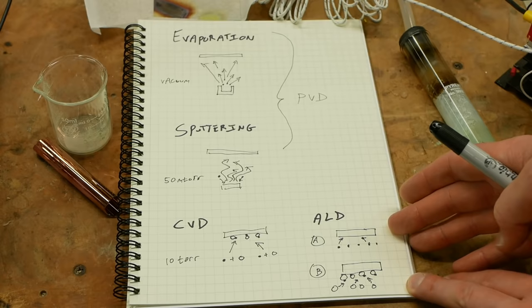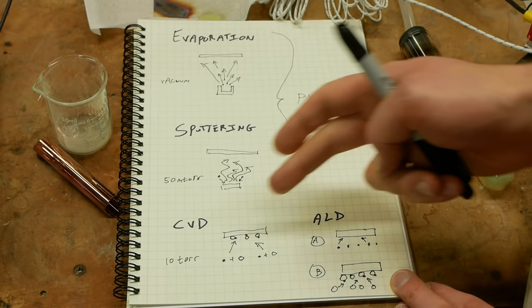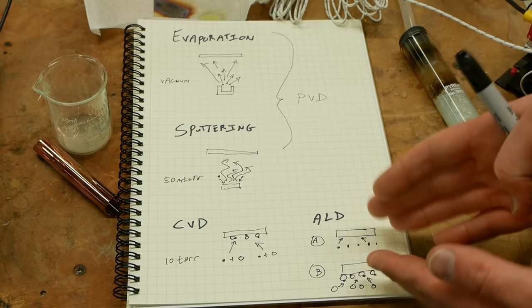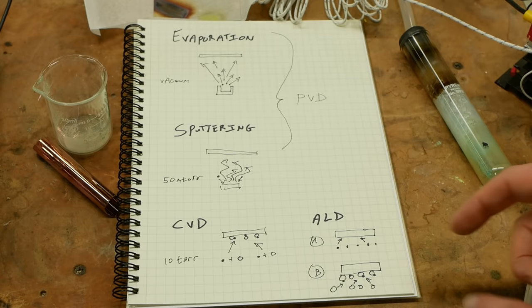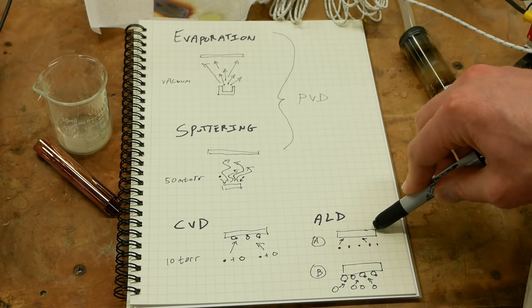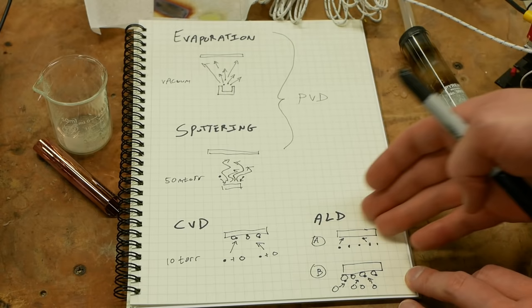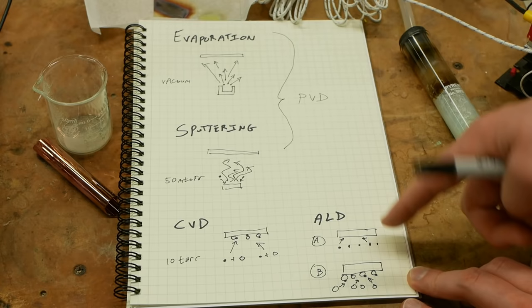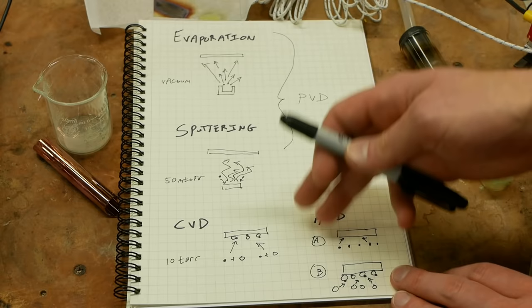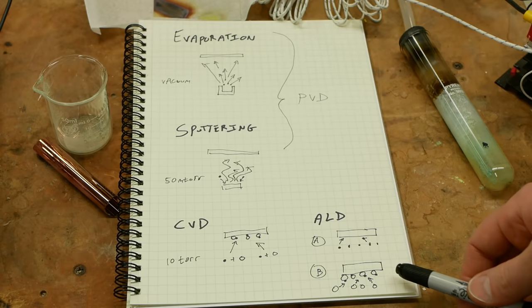So the next question is why does this A component not form like a super thick layer? Why does it only form a monolayer if we're adding more and more A gas to this chamber and we're at 10 torr and the substrate's hot? That is because the substrate is actually hotter than our source. So the mechanism by which we get this monolayer stuck on our substrate is not condensation because this is actually hotter than where this source gas A is coming from. So it's actually just plain old adhesion. We basically have to carefully clean the substrate and choose our process gases so that it sticks there in just one layer. And once one layer is down, the gas A is not attracted to itself.